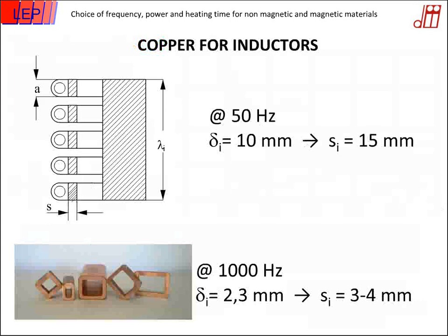This is the reason why, at low frequency, we need to use a special copper cross-section. On the upper part there is the classical inductor used for low-frequency applications, where we don't have a copper tube but a massive layer of copper cooled with an external tube welded onto the copper itself. At higher frequency, the skin depth becomes lower and the copper thickness can be just some millimeters. In this case it's quite easy to bend the copper to create the inductor, and typically we use copper tube cooled by water flowing inside.